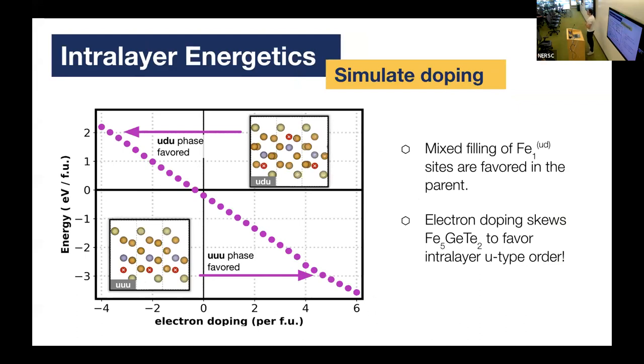But the thing that was fascinating is since we want to study doping, we want to see how that system evolves as we go up. So what we do is we consider one of these disordered sites, which I'll sometimes call the UDU motif, and then the other one is UUU, which is the simple filling one subplane. And we looked at how that changes if we manually manipulate the number of electrons explicitly given into the system. And so the idea is that there's probably some site sensitivity to it, like where the cobalt sits in one of the Fe1 sites or the Fe3 sites. But the goal here is just to say, hey, if we introduce more electrons, does the ground state shift within the intra-layer ordering of these sites? And the evidence here is showing that as we introduce more electrons in the system, when we introduce either cobalt or something else that's higher valency, suddenly we're starting to prefer this all up fill, which just as a friendly reminder, that's the low symmetry that we require in order to have this non-collinear spin texture in order to get skyrmions. So this is something that's reassuring showing also that we would expect to get the more exotic spin behavior when we introduce more doping.